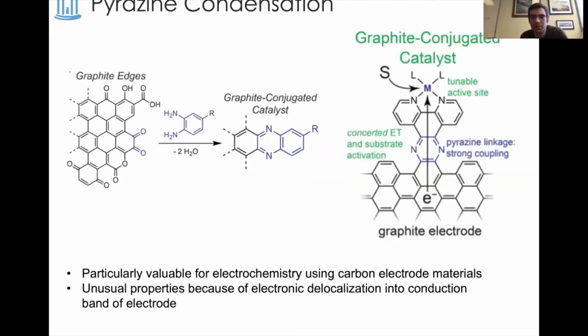So one example, also built on carbon, takes advantage of the imperfections, if you will, on graphitic materials. This is work pioneered by Yogi Surendranath and his group that took advantage of the presence of these dione units in graphite materials and built catalysts that have these diaminobenzene groups, and they undergo a condensation to form these pyrazine units. And that allows for a very direct attachment of the catalyst to the graphite electrode. And considering the prevalence of carbon materials in electrochemistry, it's quite valuable for those studies.